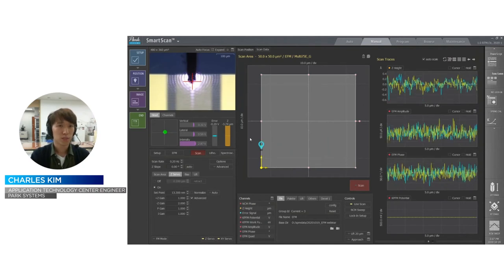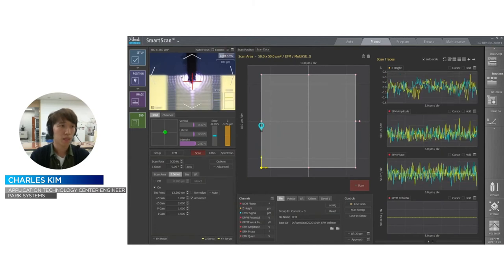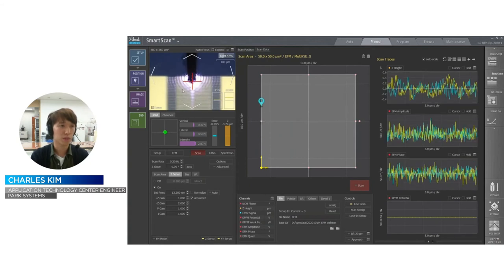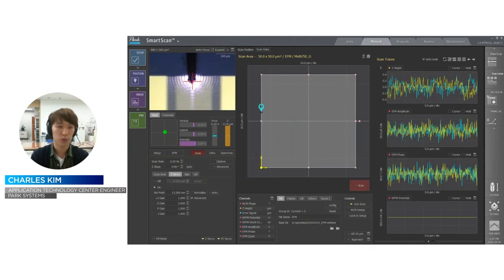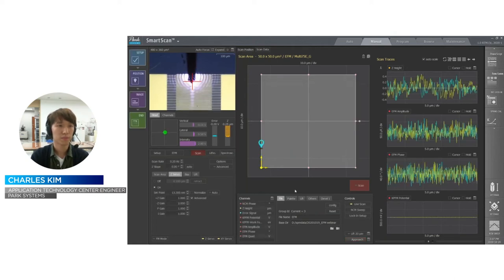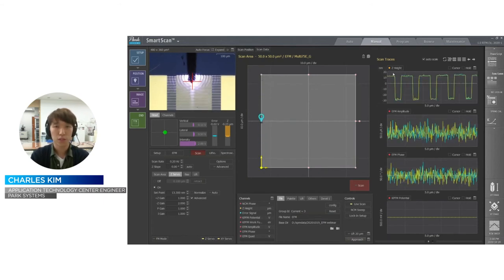So this is the SmartScan software, which controls the Park AFM system, and the sample and the cantilever are already mounted and prepared here. But the tip is now far from the surface, so let me approach to engage the tip close to the sample surface. Then now the line scanning is started. Then you can see the Z height signal from the top over here.